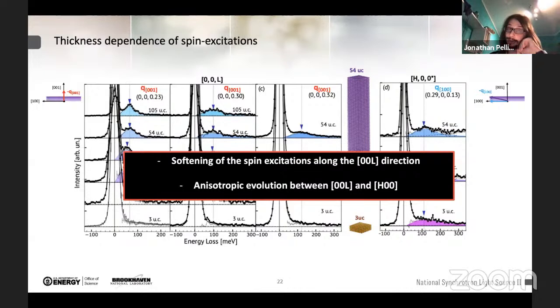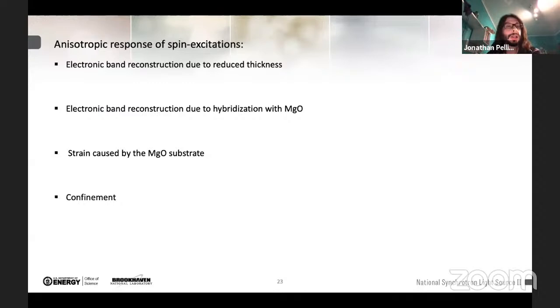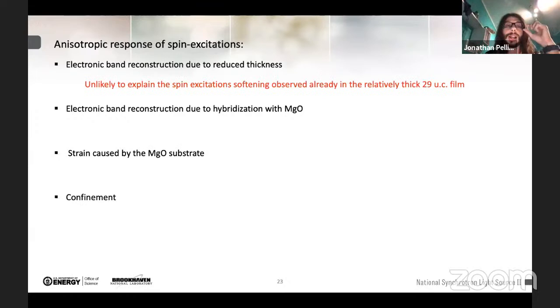Now, we have to look into possible reasons that could lead to this anisotropic response of the spin excitation. We thought about the possibility of an electronic band reconstruction due to the reduced thickness. However, this is unlikely to explain our observed trend, because we observe a softening of the spin excitation already in a film that is 29 unit cells, which is relatively thick.